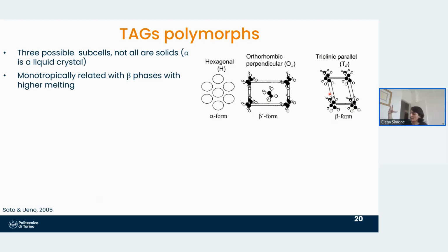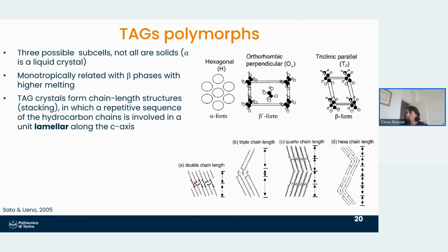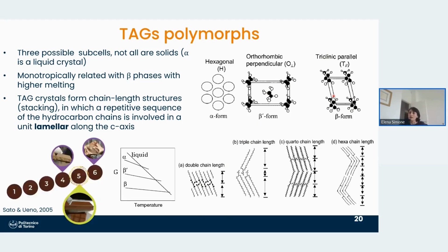Then if we look at our TAG crystals from the side, we can also see a different type of stacking, the way that molecules are arranged close to each other. So we can have a 2L stacking, 3L stacking, or 4L and so on. Every mixture of TAGs or pure TAG will have a specific combination of subcell and type of stacking. So we can see 2L alpha forms, 2L beta prime forms, 3L beta, depending on the structure of the molecule. Cocoa butter, chocolate, has 6 different polymorphs, which are all a combination of different type of stacking and subcell. What we want is form 5, which is a beta polymorph with a 3L d-spacing, lamellar spacing.